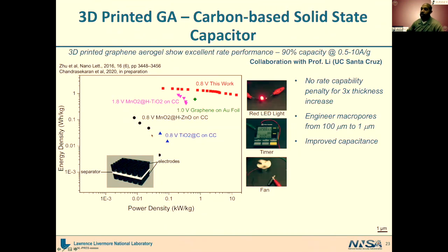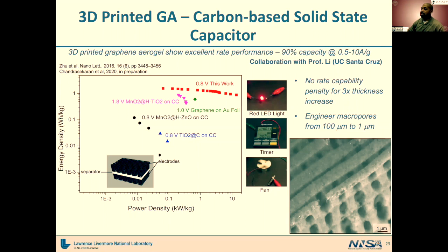And here just showing some of our early data that we were indeed able to now have here again, energy density versus power density, having an electrode that is fairly thick. Again, this one is 1 millimeter thick. But because it's 3D printed and the ligaments themselves are only on the order of a few hundred microns, you're able to push to high power densities without having that falloff that you typically would get with a thick electrode. We're continuing to push the boundaries here, getting to even smaller macropores. Our target really is in that 1 to 10 micron range. And so this is work that one of our other scientists is really focused on.